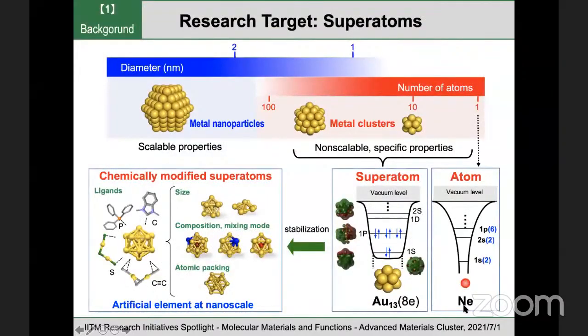Our research target is very small metal clusters composed of fewer than 100 atoms. We call these small clusters superatoms because of the similarity in electronic structure with conventional atoms. By surface protection with ligands, we can treat these superatoms as conventional chemical compounds. And we treat these chemically modified superatoms as artificial elements at the nanoscale. We have 3 projects on this type of target.